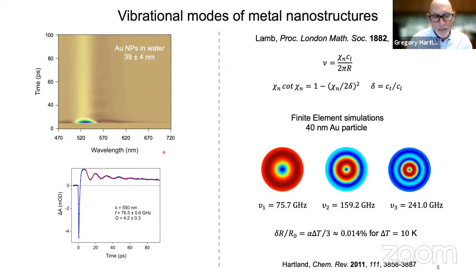That's pretty lousy, and it's because in the sample there's a whole bunch of different size particles. Each one of those particles has a different period. When you add up all those periods, you get a damping in the ensemble measurement. Okay, you can calculate the frequency either using analytic expressions if they're available, or again doing finite element simulations.